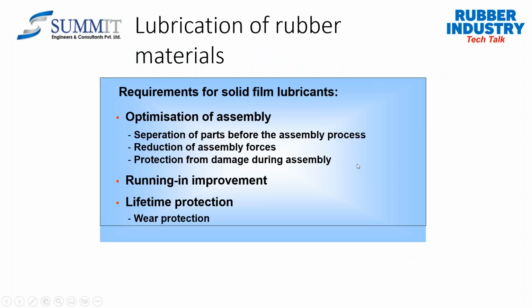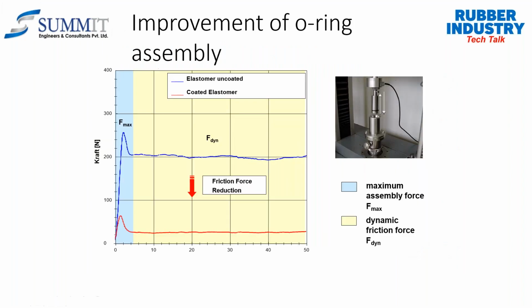We have taken certain examples here, wherein we have compared an uncoated O-ring and a coated O-ring. If you are able to see here, the blue graph is showing the maximum force of approximately 250 Newton, which is required for the insertion of the O-ring into the shaft. Whereas with the PTFE coated O-ring, you will find less than 50 Newton force, which clearly shows the friction force has been reduced.